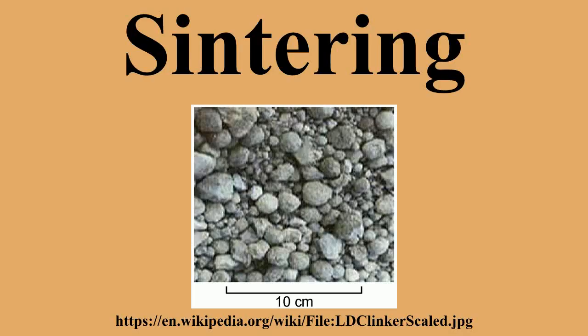In rate-controlled sintering, the densification rate in the open porosity phase is lower than in the CRH method. By definition, the relative density ρREL in the open porosity phase is lower than 90%, although this should prevent separation of pores from grain boundaries. It has been proven statistically that RCS did not produce smaller grain sizes than CRH for alumina, zirconia, and ceria samples.